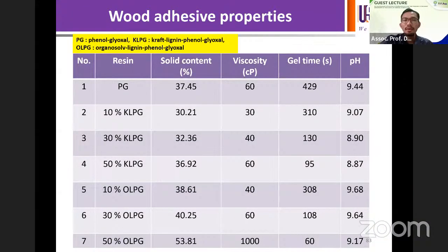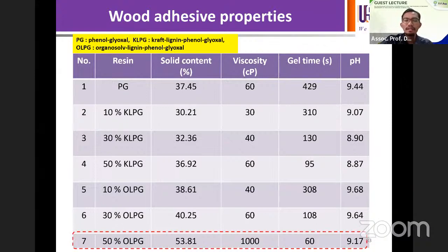So what we have obtained is that we characterize the properties of the adhesive. As we increase the content of the lignin, especially for organosolv lignin, the solid content and viscosity are better. The higher the viscosity, the better the gel time. So what does gel time mean? It is the curing rate of the adhesive. If you have a shorter curing time, it means the time required for the adhesive to harden is short.